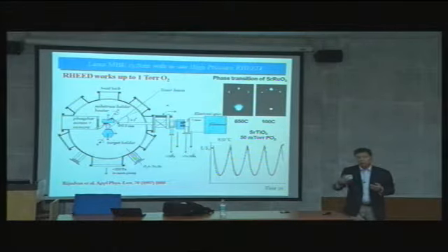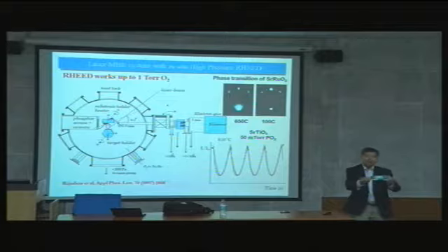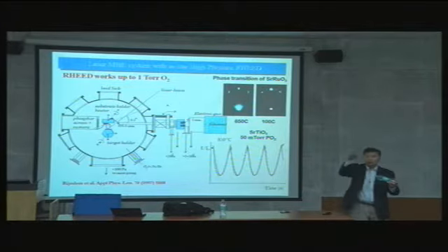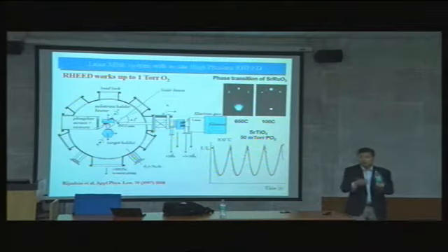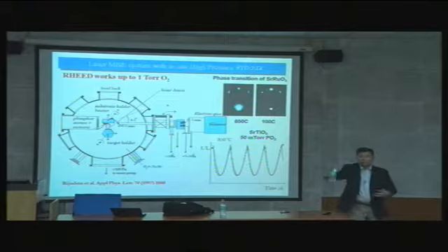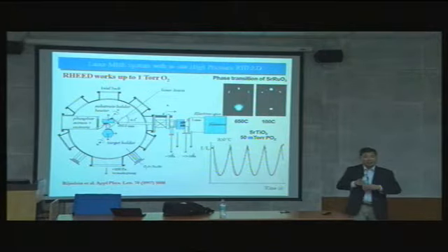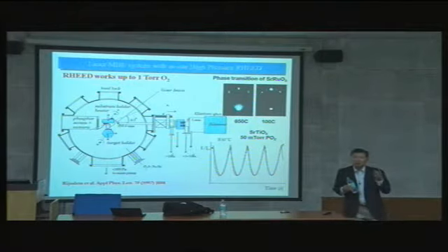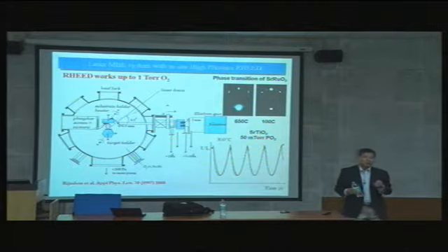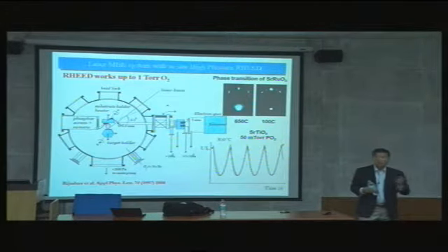How do you overcome this problem? The laser normally comes this way, and I think this is a trick that we have learned: you rotate this beam. The excimer laser has a rectangular beam profile, and different lasers have different ones. So you rotate the beam from this orientation to this, and then your beam comes this way, and you are less likely to have over focus and under focus. You understand that? It's a lot of very trivial things in thin film growth. A lot of people just ignore small details that make a big difference in the quality of the materials you grow.